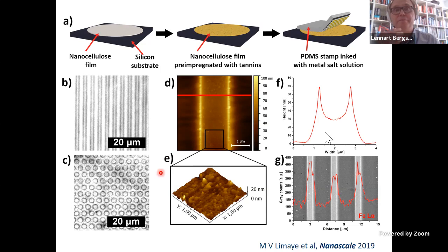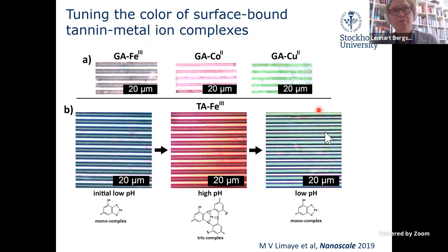We first impregnated the films with tannins, and then we print it with the metal salt solution. As you can see here, we can definitely react the iron with the tannins, but because of de-wetting issues, this mainly occurs at the interface here, or the edge of the pattern materials.